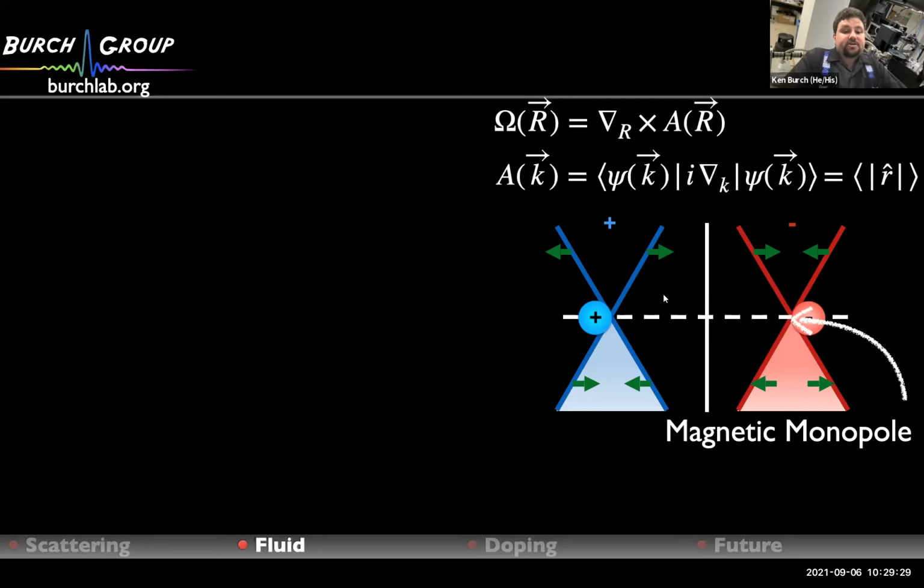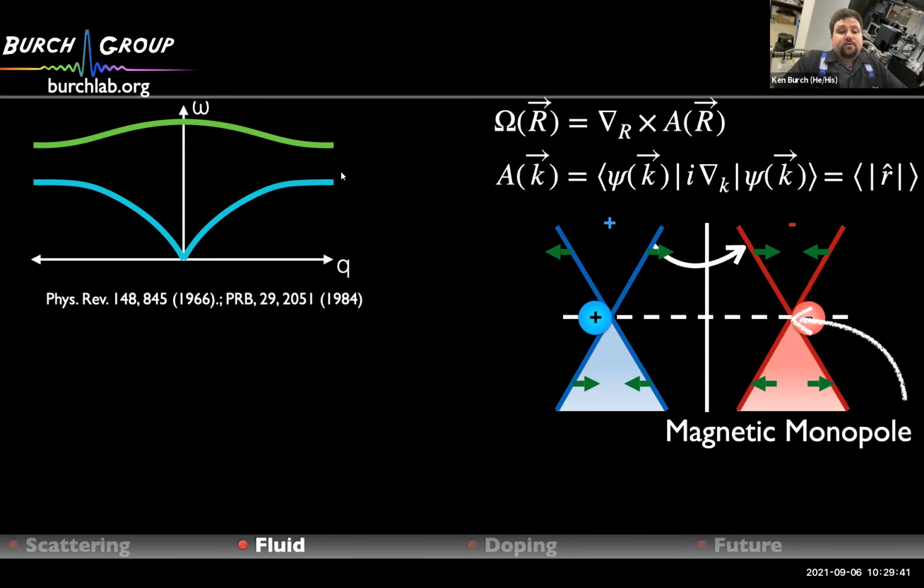Perhaps more relevant to our transport discussion, it also seems that phonons are going to be the very natural way that you would go from one chirality to the other, and could be how you would relax transport or chirality in general. So what you might expect to see is, if the phonons scatter only into other phonons, you'd basically see by anharmonic scattering that the optical modes, for example, would decay into a pair of acoustic modes. And you would just see that the temperature dependence of the lifetime is governed by Bose statistics. In other words, it would just keep growing with temperature, because these are bosons and the chance of making them just gets better and better with temperature.